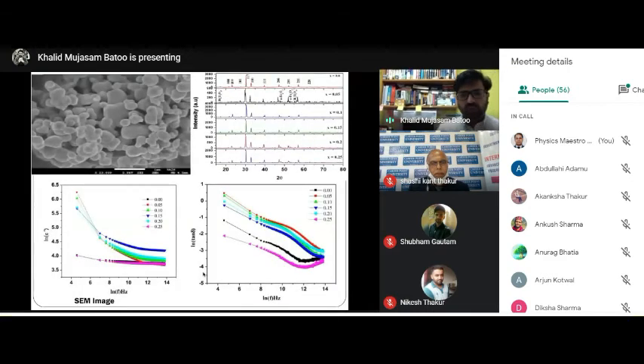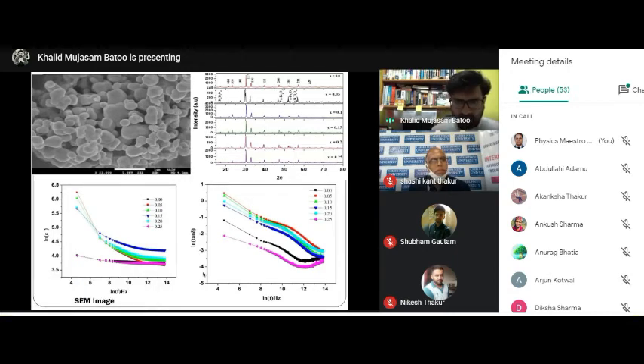Looking into this aspect, we prepared a material. The nanoparticles prepared are almost spherical in size. They had, in the composition of 5%, some impurity phases - unwanted, unfortunately, but they were there.